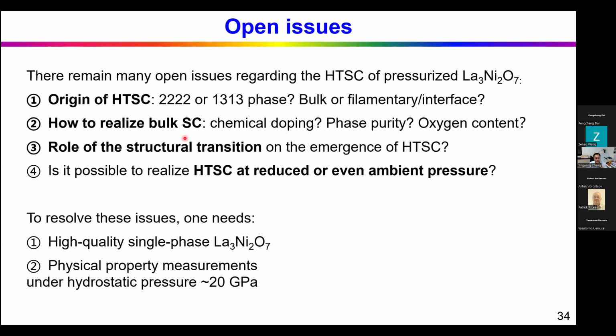And is it possible to realize bulk high TC superconductivity by controlling the phase purity and oxygen content? And what's the role of the structural transition? And is it possible finally to realize high TC superconductivity at lower pressure or even ambient pressure? So to resolve these issues, the important thing is we need high quality single phase samples, not to mention single crystals. We need single phase 3-7 phase samples.